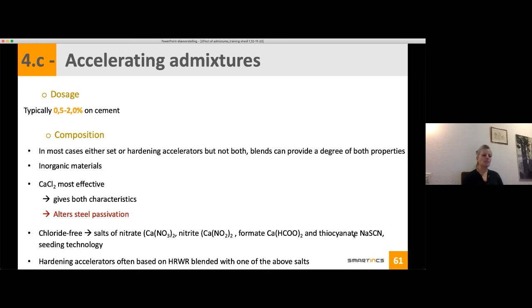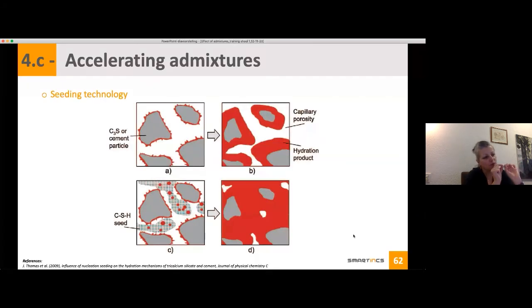And more recently, you have seeding technology. And what is seeding? For instance, you have small particles that you can add in your mixture that act as nucleation points. On the top of this picture, you can see a normal hydration. You have your cement particles, and at the surface you have some cement hydration. With time, the hydration product grows from your cement particles.